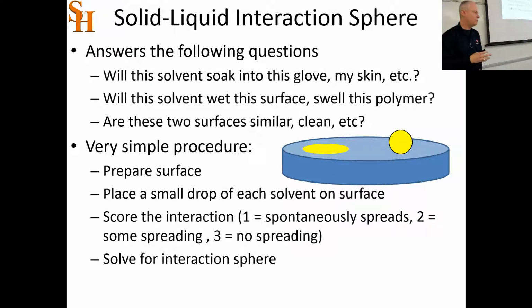Now this is the same sort of analysis, but using contact angle. So here I put drops of different solvents on a surface. I used glass, and this is in the notes for today. We will go more quickly through this because it's essentially the same thing with the spreadsheet. But here, instead of percent weight, I used whether it wetted or not. So you put the drop on there. If it spreads spontaneously, that's interacting with the surface. If it beads up, that's not interacting with the surface.